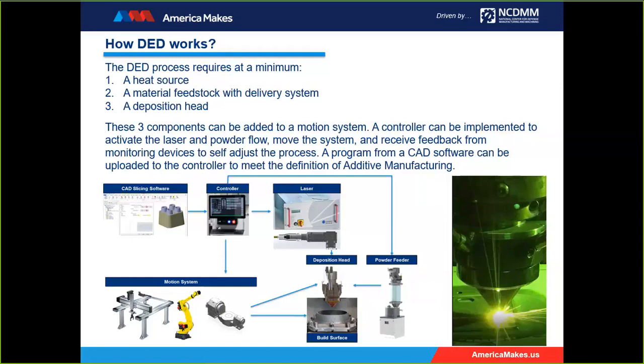You also need a CAD-CAM slicing software package, which will take your 3D model and slice it, and our controller runs on G-code, and that tells the machine where to be and when, and how fast the powder should be coming out, and the power level for the laser. And then powder is pulled from the powder feeder, goes into the deposition head, and is controlled from that controller through the motion system to build up the part layer by layer.